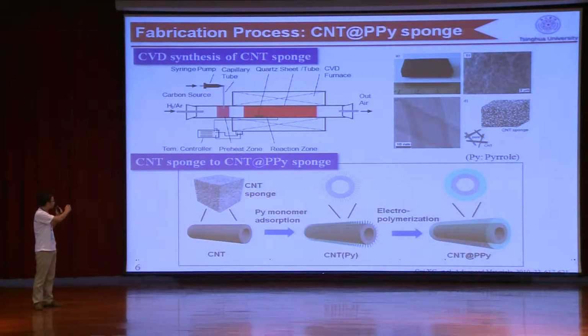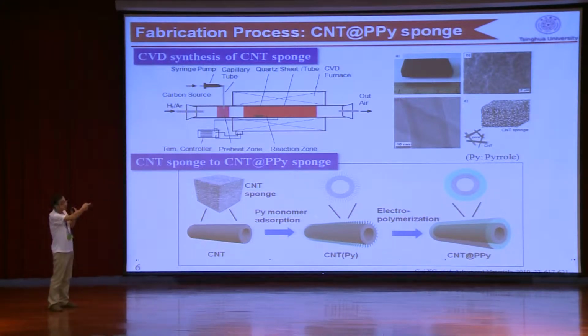The fabrication starts from the CNT sponge synthesized by chemical vapor deposition. This is a schematic for the CVD system, and this is a figure. It shows a block of the CNT sponge. It's light, porous, and flexible. And more important, the porous structure can provide a general platform for functional materials deposition. So we introduced PPY, polypyrrole, a typical and environmentally friendly conductive polymer usually used to enhance the supercapacitor performance.